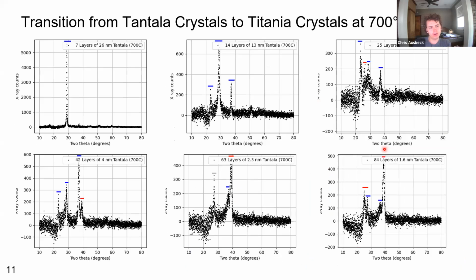Now, one thing to note is that there is a transition from tantala crystals to titania crystals among the samples. So I've taken a snapshot around 700 C to show this. At 7 layers of 26 nanometer tantala, this is our thickest samples, they tend to be tantala peaks. So we have our main tantala peak here. At 14 layers of 13 nanometers, we still have our tantala peaks. You see these other ones emerge as well, around 36 and 23 degrees, but they're all still tantala peaks.